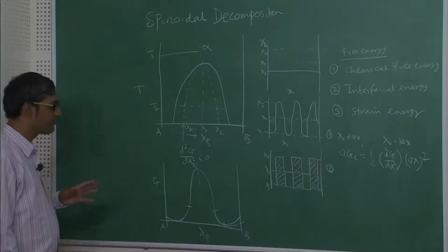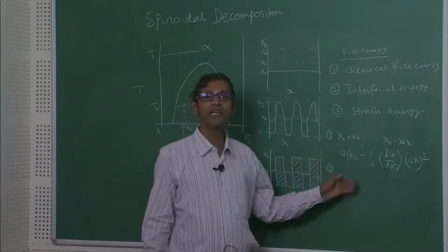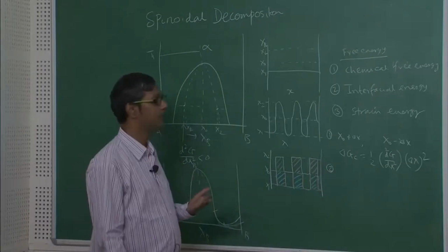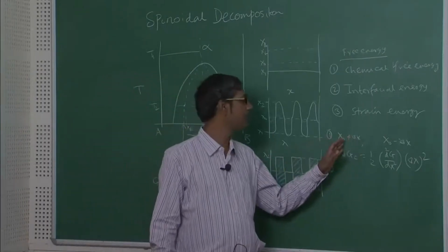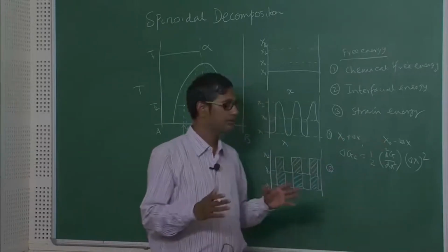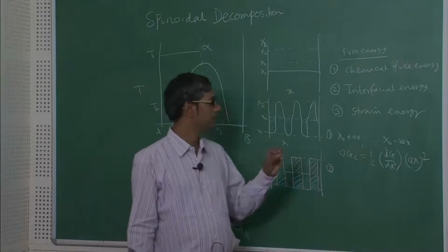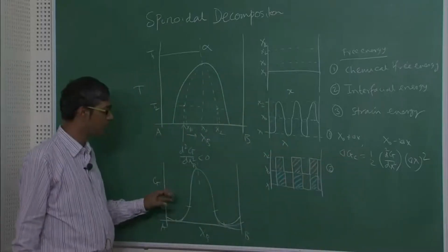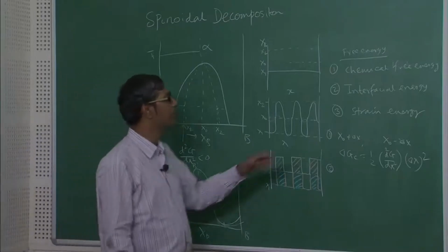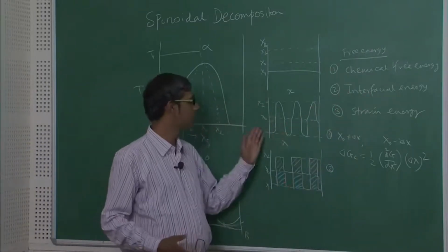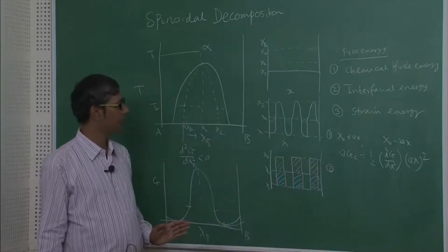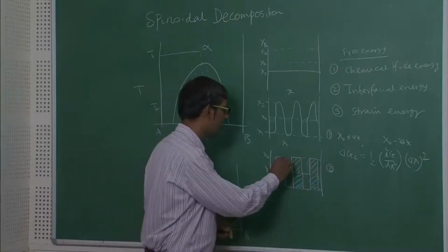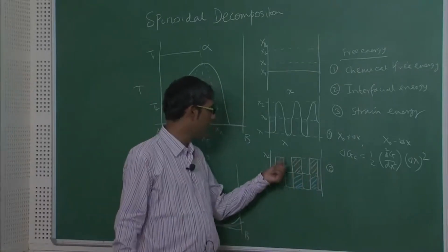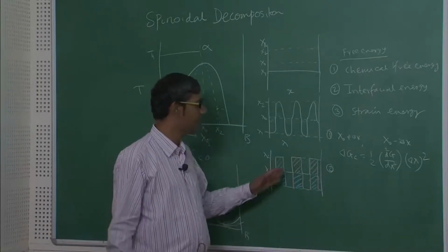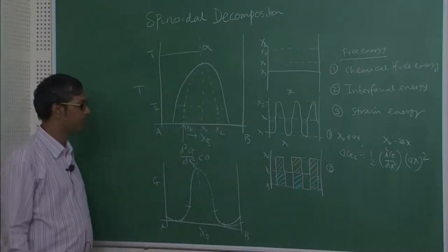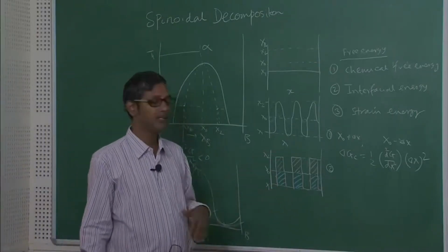So, now the question is this, if this is the situation, the interfacial energy is basically because of the dissimilar atoms present in the system. Even at the beginning when the decomposition is happening with X0 plus delta X, X0 minus delta X, these regions are finely dispersed, still there will be clustering of dissimilar atoms or basically presence of dissimilar bonds which will lead to interfacial energy. And as the system grows, they are becoming more and more A and B rich. So, suppose this is an interfacial boundary where you have B rich region and A rich region sitting side by side, and this leads to bonding between dissimilar atoms, and these dissimilar atom bondings will lead to higher interfacial energy.